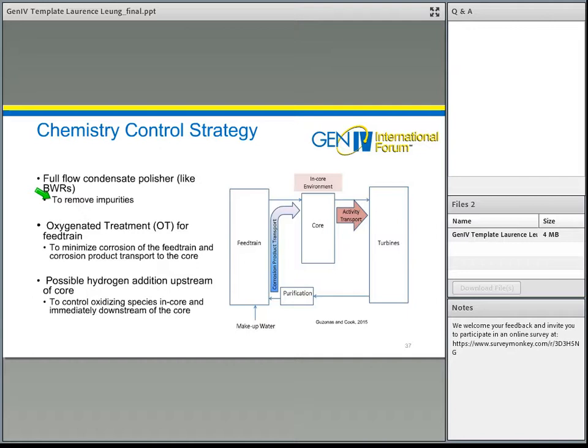And you use oxygenated treatment for the feedwater in this area, and then possibly introduce hydrogen addition upstream of the core. This is to control the oxidizing species in the core so that you can minimize the activity transport to the turbine or through the cladding.